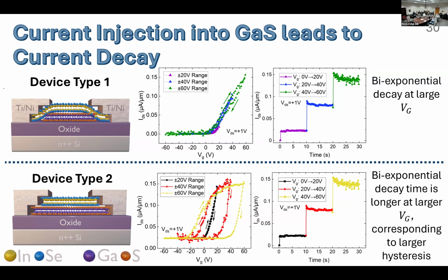The shift in the hysteresis is also related to the voltage range that you apply, right? Depending on the range that you apply, that will determine how many traps are inside. So if you go to a higher voltage range, you'll increase the number of traps in here. Hence, you will have a larger width of this hysteresis. Whereas if you limit it to, say, plus or minus 20 volts, you do not see this. Does that answer your question?